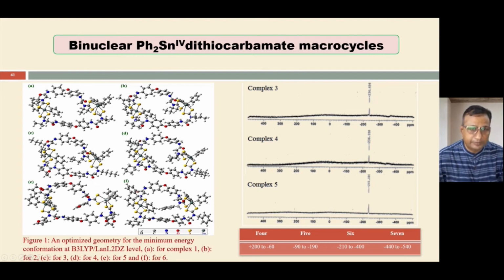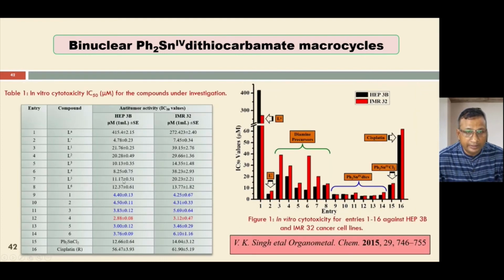All the molecules are optimized by DFT level calculations, and the structural parameters obtained theoretically compared well with the similar parameters obtained experimentally. And then we screened all the molecules for their potential anti-cancer activity against hepatoma and neuroblastoma cell lines, HEP3B and IMR32. And we observed very interesting anti-cancer property particularly for metallo-macrocyclic compounds holding diphenyltin centers.